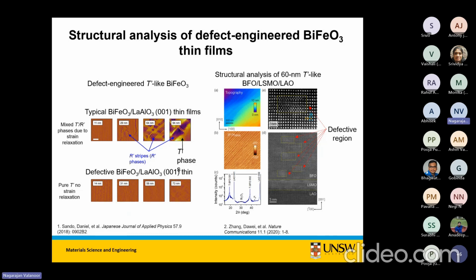So the system is a very beautiful example of how nature manages to self-create, self-accommodate. So bismuth ferrite is imposing the same strain as the underlying lattice, underlying substrate, sorry, such that through the entire thickness, you will not find any relaxation of dislocations or mixed phase. So it's T phase, the tetragonal phase, right up to, we've gone up to 100 nanometers, but above 70 nanometers, the surface begins to deteriorate because the bismuth now is really going through the surface. It becomes quite pitted. So 70 nanometers will give you some really nice stripes, and then around 70, you can start to see sometimes there will be these small pockets.